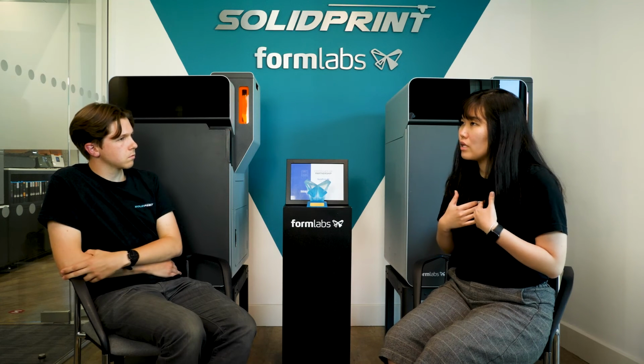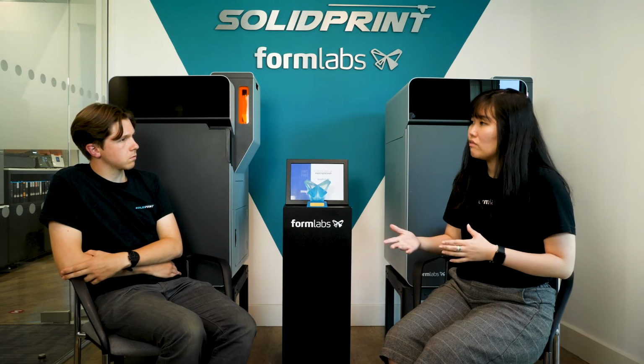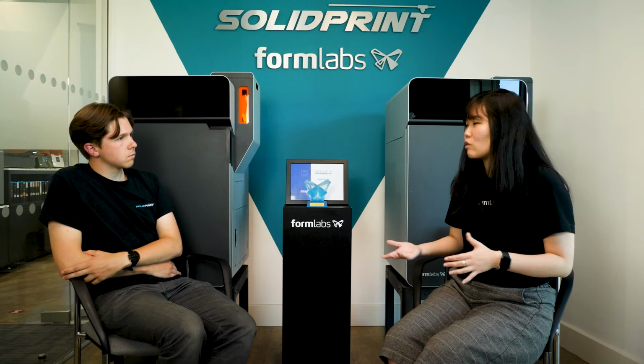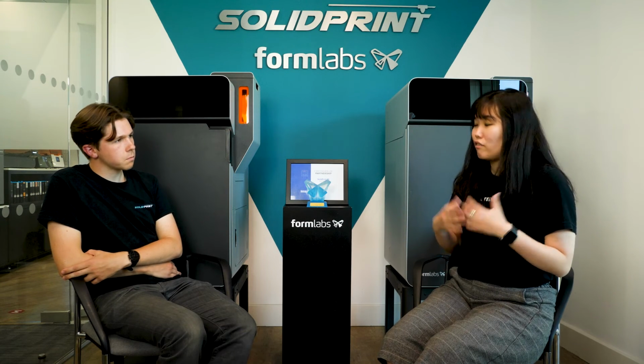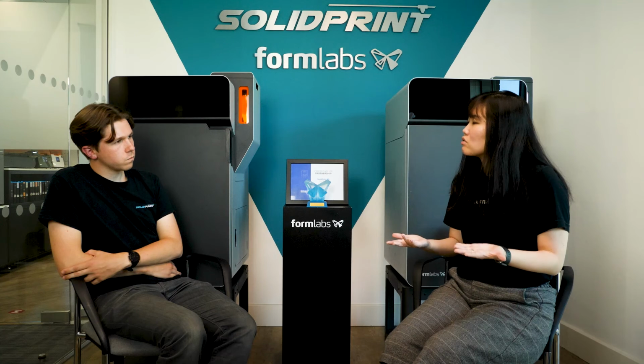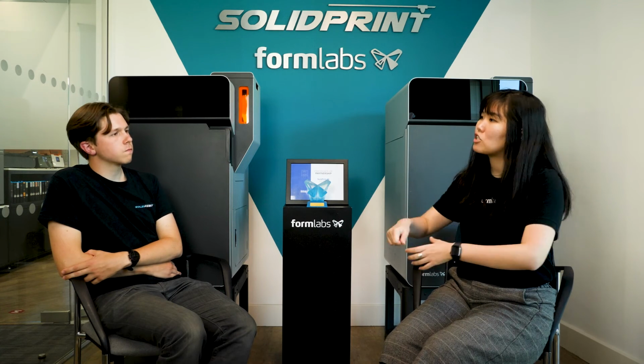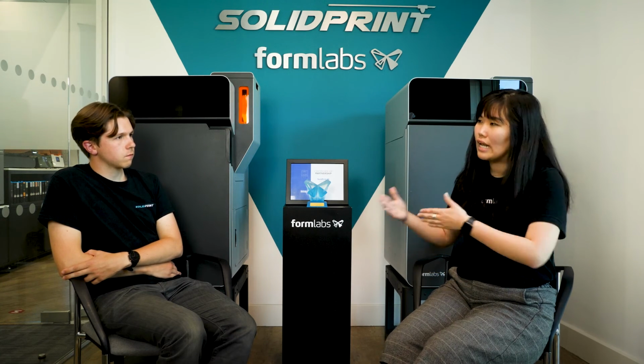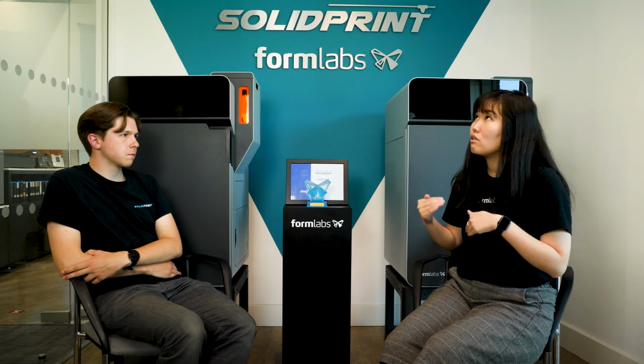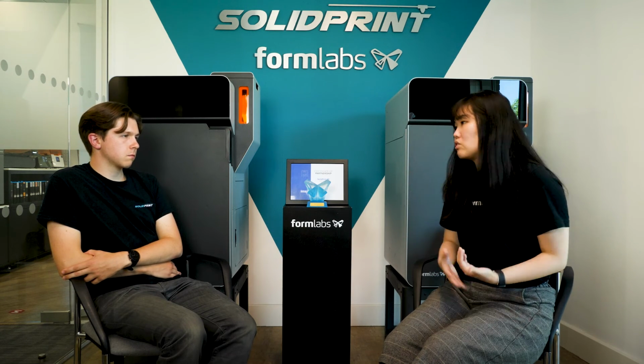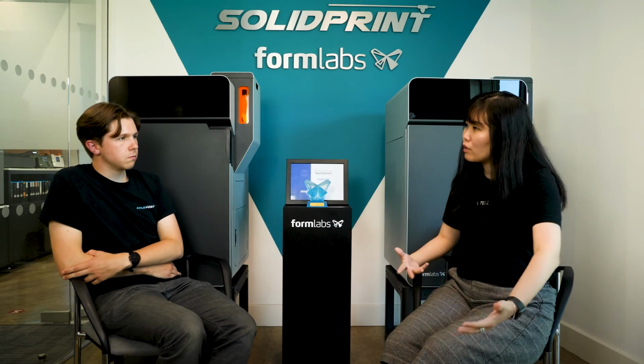However, if I were running the same print on Nylon 11, let's say, which has a recommended refresh rate of around 50%, if I'm doing a 10 kilogram print, 5 kilograms is reclaimed, 5 kilograms is new. So you could imagine opening a new bottle of new powder just to start the next print. Yeah. So having a very low refresh rate is always going to be better for you. And that's where we are quite competitive.